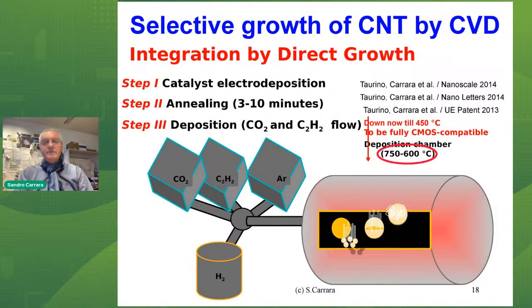How to do it? Well, there are different options. We can use, typically, chemical vapor deposition, which is typically used to grow nanostructures on top of our multi-panel system. You can see here, depending on whether we move from a non-compact or a very compact precursor film, typically done by using iron or cobalt, we can reliably grow multi-walled carbon nanotubes on the working electrode, or even graphene nanopetals, starting from the same catalyst but deposited in a slightly different manner on the working electrode. Then we can grow selectively the kind of nanomaterial we desire.